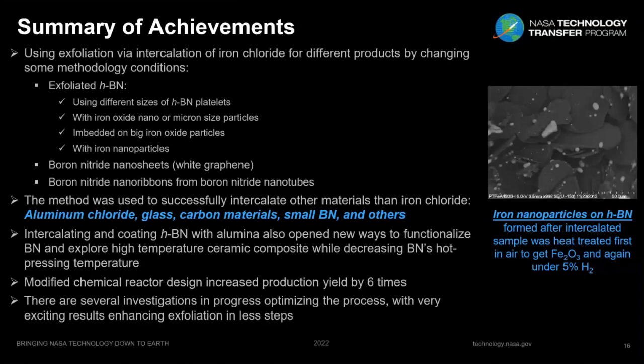The ones that I'm showing here in the picture were formed after iron chloride was intercalated. It was heat treated at high temperature in a gas with 5% hydrogen, and we created iron particles on hexagonal boron nitride. That was pretty cool. We can use this product to create boron nitride nanosheets or white graphene. We can create boron nitride nanoribbons from boron nitride nanotubes. This method was used to successfully intercalate other materials than iron chloride, like aluminum chloride, the one that I demonstrated, but many others like glass, carbon materials, small boron nitride, and others.